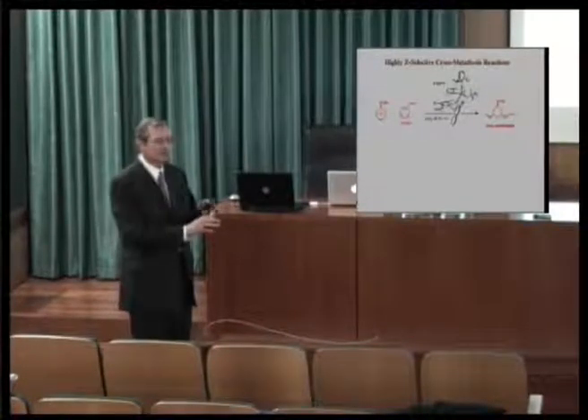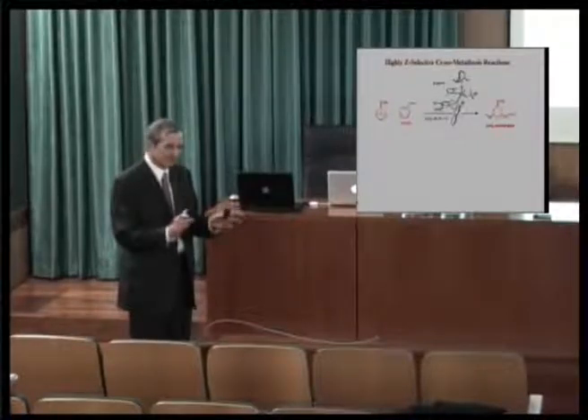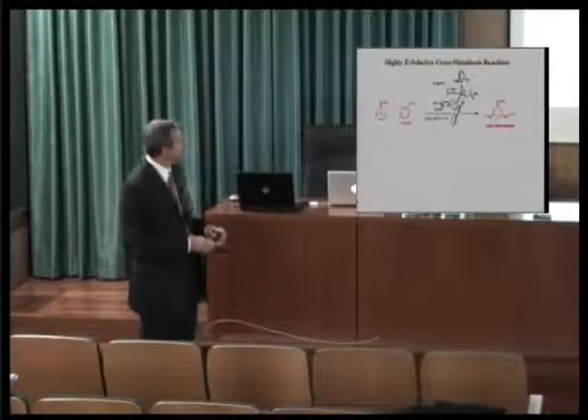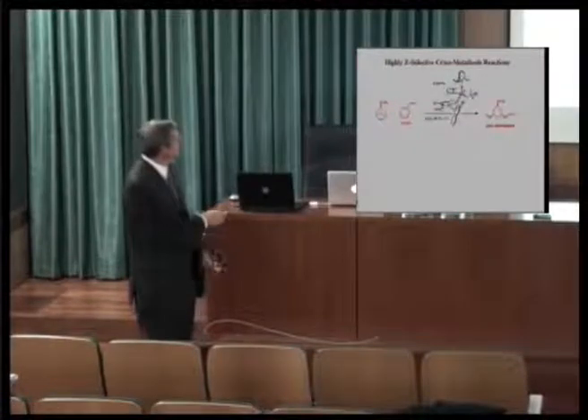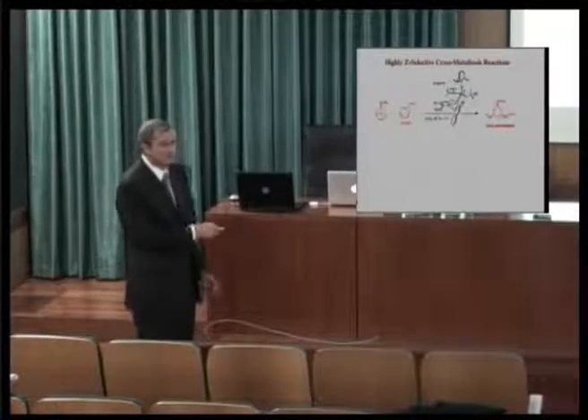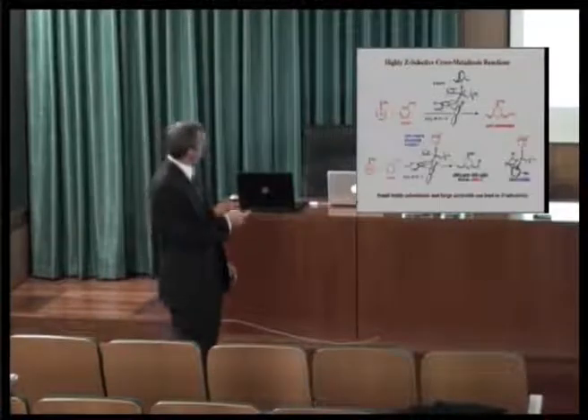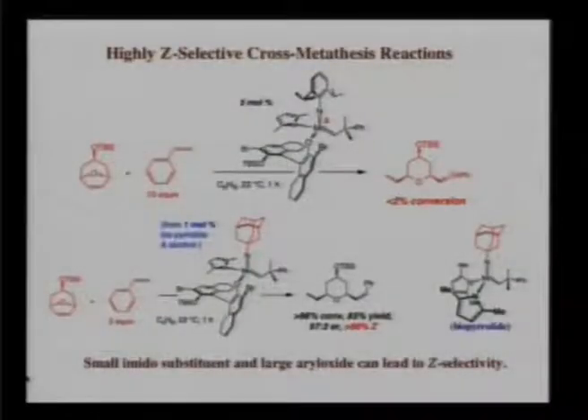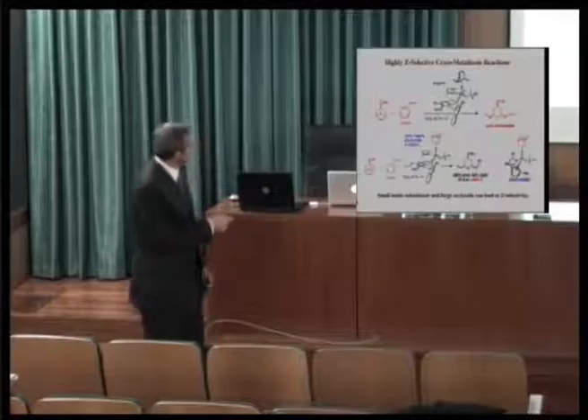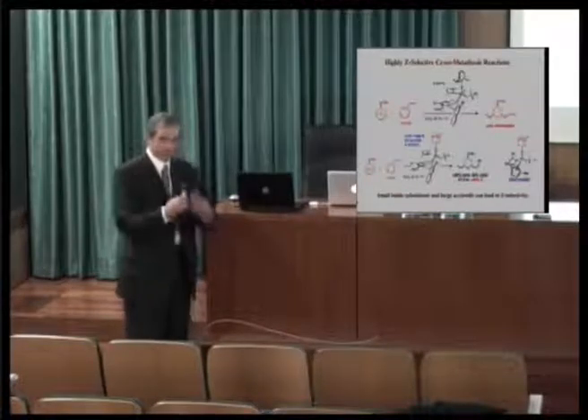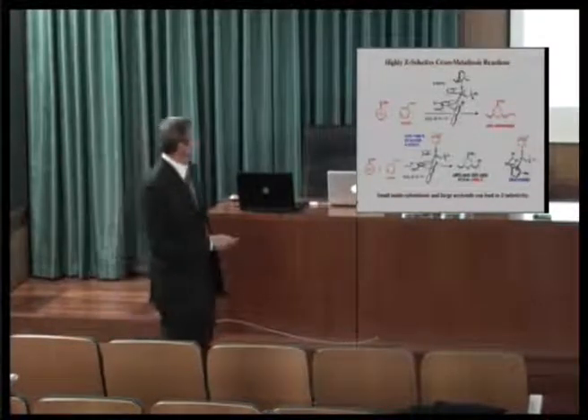It's very characteristic of these new catalysts because they are very, very sensitive in many ways to everything around the metal. And so to find that some reaction doesn't work is not surprising. If you change the amido group to adamantyl amido, then the reaction does work very well, greater than 98% conversion, 85% yield, 97% EE, and this double bond is cis. That was a surprise because normally trans is the double bond that is formed.